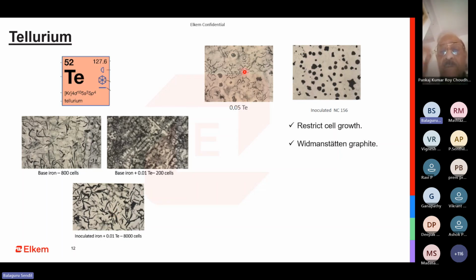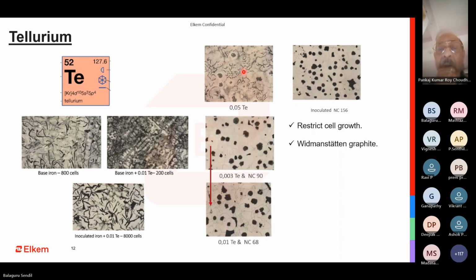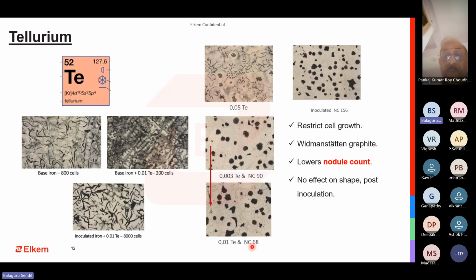If I add this much, it is going to kill my nodule shapes. Okay. Then I am going to inoculate it. At 0.003, my nodule count is 90. At 0.01, my nodule count has dropped to 68. What it does is very similar to the previous element, lowering the nodule count. It doesn't have any impact on the size and shape of a nodule. It only lowers the number of nodules available to be qualified as a good nodule.